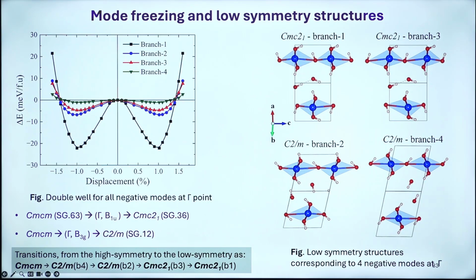How do you know there are only 4? Because the entire phonon band seems to be negative. Yes, but that is a K path; the branch is what we are trying to freeze. At that particular point, we take each branch and displace it, compute the phonons, regenerate the structure, and see what corresponding space groups it gives. I am trying to address a temperature induced structural transformation, which is not possible with normal DFT. For example, I have a structure formed at room temperature, and when I do the phonon dispersion, I get imaginary branches, so I cannot capture the physics properly.